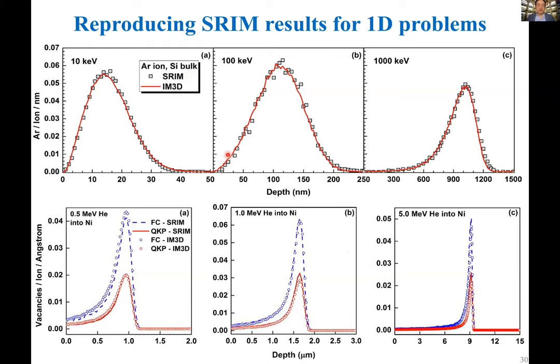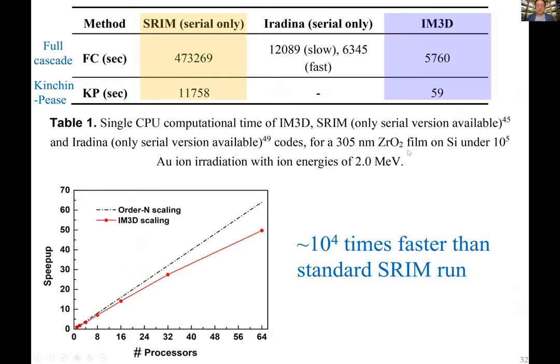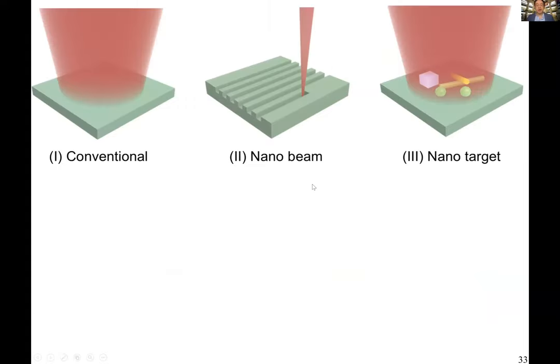So this IM3D code is able to reproduce, for example, argon ion implanting into silicon. We're able to reproduce the doping profile. The smooth line is our code, and the symbols are from SRIM. And for both the full cascade version and the quick Kinchin-Pease version, there's a factor of two difference, and we can reproduce both of them. And this is parallelized, so we can run 10,000 times faster. Something that traditionally takes an overnight run now just takes minutes on a parallel computer.